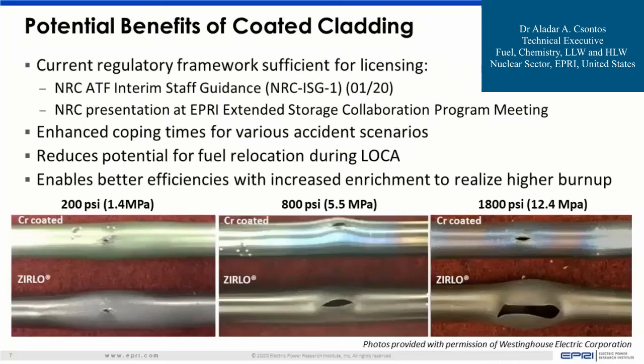That was very informative and very useful for us. The enhanced coping times I talked about earlier, reduced potential for fuel relocation. Here are LOCA experiments that were provided by Westinghouse Corporation, looking into the chromium coated versus the Zirlo. And you can see here that the burst opening sizes are much smaller than the Zirlo, which then reduces the amount of fuel relocation during LOCA. And that then enables us possibly to go to higher enrichments to realize higher burnup. And that's a key aspect of this work.